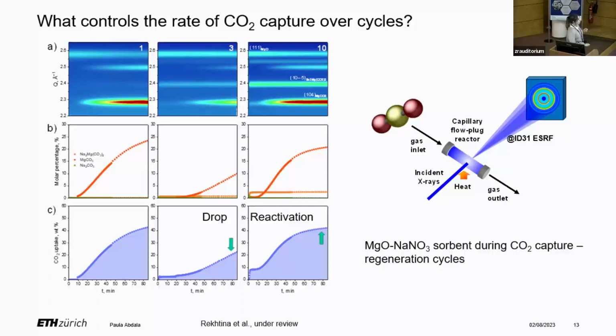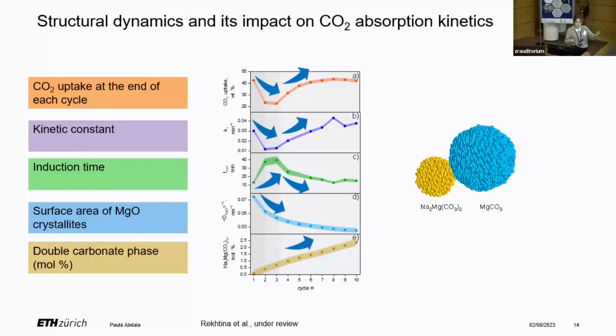So with this, we can also calculate the CO2 uptake. In the first cycle, we have a relatively high CO2 uptake, which dropped in the second cycle. And at the end, in cycle 10, we observed a reactivation of the material. So we can extract parameters that tell us about the performance and some structural parameters for each cycle and try to understand correlations here. The CO2 uptake is high at the beginning, then decreases in the second and third cycles, and later increases again. Now from the kinetic analysis, we can also obtain a kinetic constant and an induction period. We see that the kinetic constant, which tells us how fast the magnesium carbonate forms, decreases in the second cycle. So this correlates with the uptake, and it gradually increases in the following cycles.